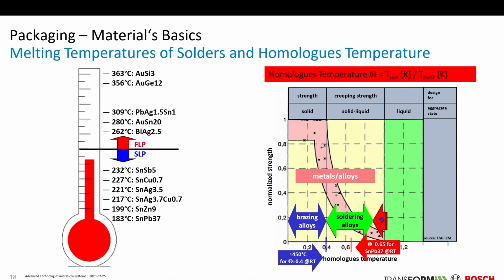Why is this important? Because these numbers refer to the demands of soldering regarding the application, the load from the application temperature. So this value of 0.4 at room temperature, referenced to room temperature, means 450 degrees C, and this is the border between the soldering and brazing world. You can think about brazing as well, but then you need really high melting alloys.